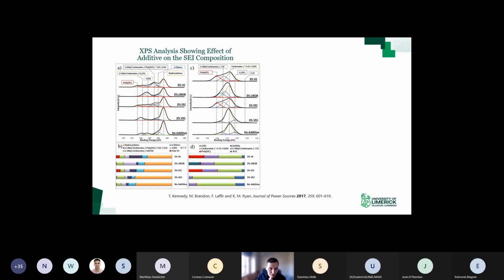We did some XPS to analyze the chemical composition of those SEI layers. What we found was, so I'll direct your attention to the C1s spectrum, that for the VC and FEC electrolytes, there was a significant concentration of poly-VC in the SEI layer. And this is something we expected because it had been shown for graphite previously and for other silicon type electrodes. But basically, what poly-VC does is it's a polymer, obviously, but it provides flexibility to the SEI layer. So if that's in there in large enough concentrations, you get a more flexible SEI layer.